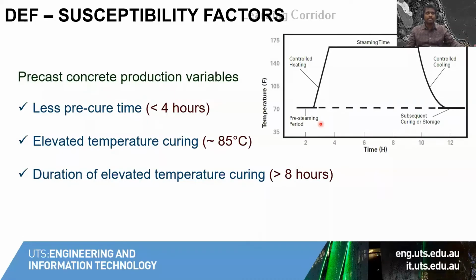the chances are the concrete will get exposed to the high temperature at a very early stage. So because of that, the early ettringite formation may itself get inhibited. So there is no room for the ettringite to get decomposed in the system, which is more vulnerable to the ettringite decomposition and re-forming reaction. So the lesser the pre-cure time or the pre-steaming time, the more will be the vulnerability of the concrete.